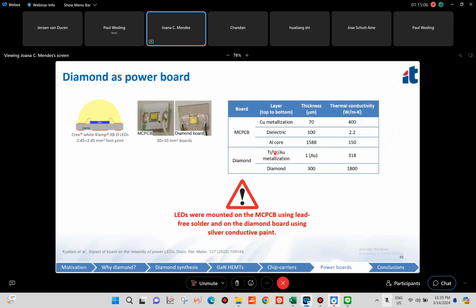However, we had a really hard time when we tried to solder the LED to the diamond board. So we tried to use a lead-free solder, the one that we use to mount the LED on the metal core printed circuit board, but we simply could not bond or solder the LED to the diamond board, probably because this thermal conductivity is so high that the heating cycles were not adequate. So we'd really have to optimize the soldering process. However, after a couple of trials, we saw that the gold metallization had been taken away. We only had titanium and tungsten with a very high track resistance.